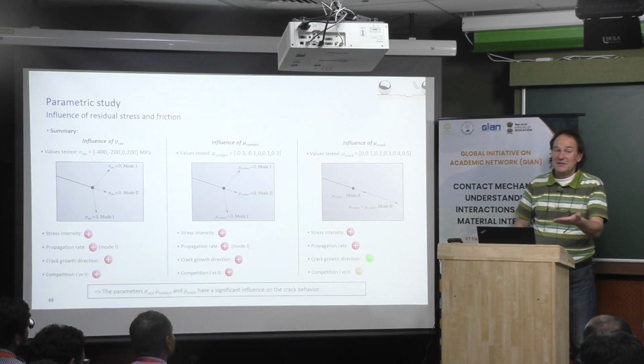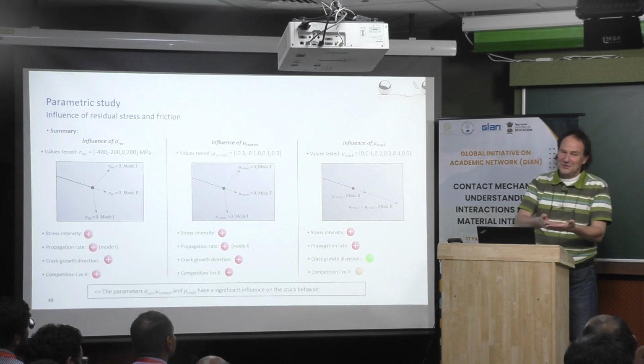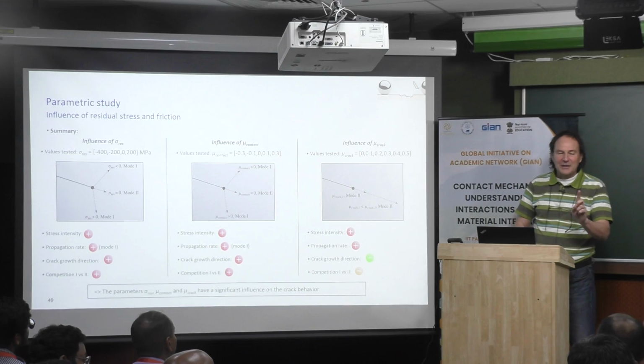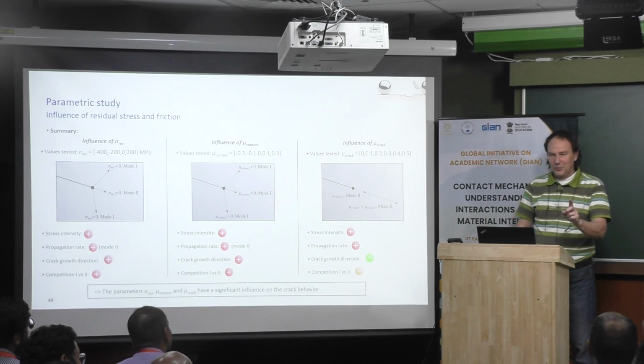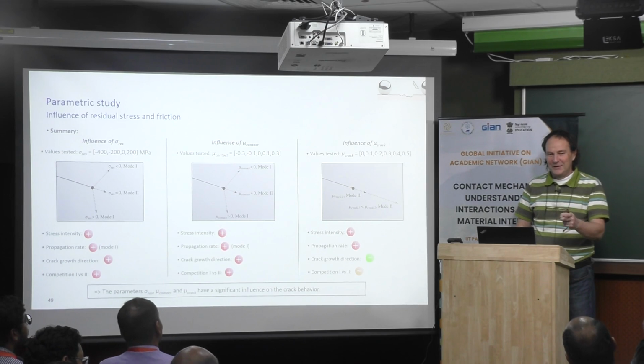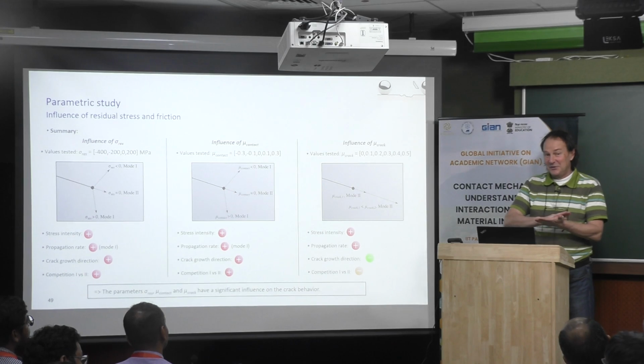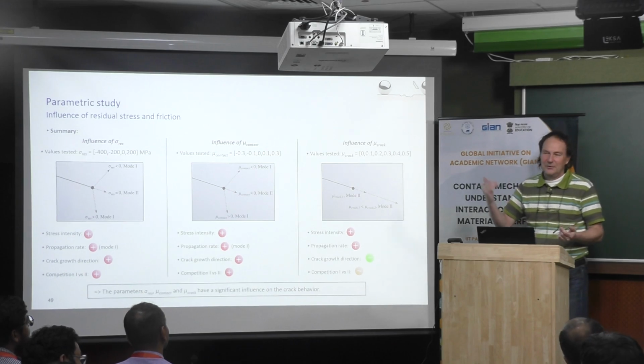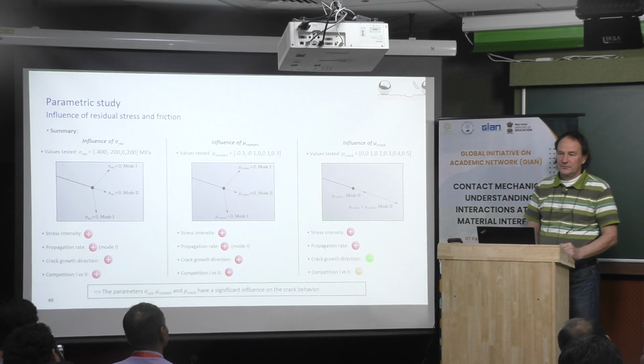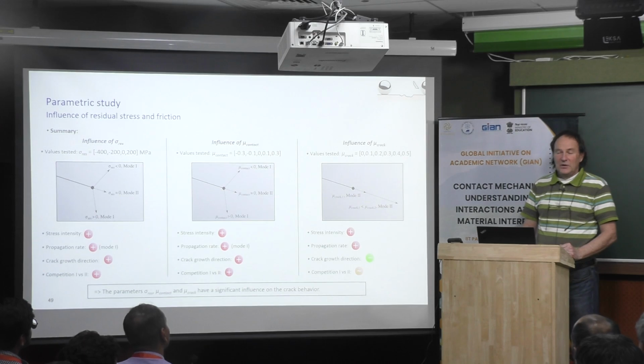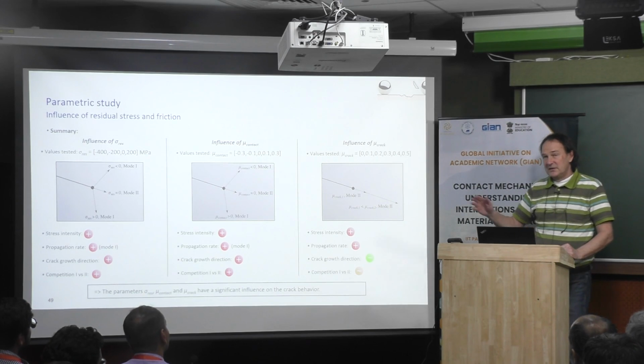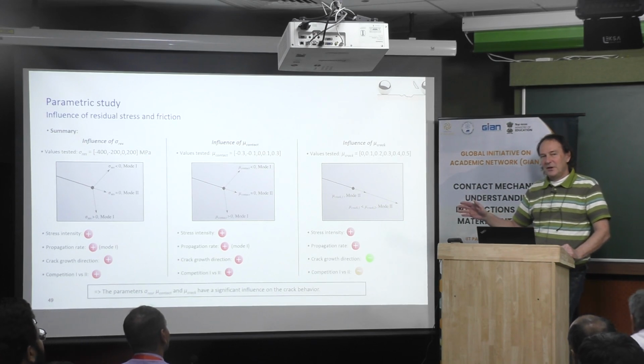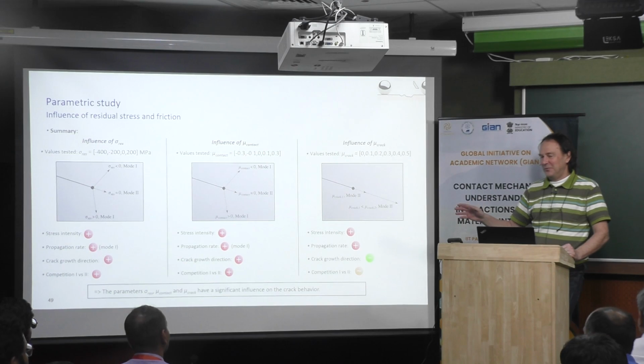And when you observe some facies of failure of crack, except if you work on monocrystal, on crystalline materials, you can see something which is very flat, but not for metals like that. Why was there not any plastic zone created ahead of the crack? We do not consider plastic domain. In fact, this is what we call linear fracture analysis, linear fracture mechanics.